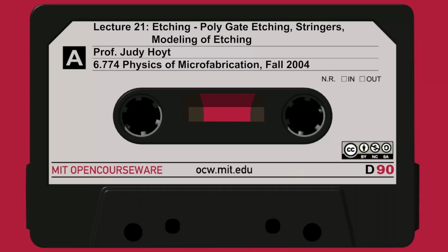So this is an example of how they got rid of the notch. This notch is not as bad or doesn't look as dramatic as the one I drew on the board. They got rid of it by just changing a few things. They changed the pressure and the flow rate, and they're able to get a more vertical type of sidewall. So if you have to do polysilicon gates, you'll find yourself twiddling a lot of the knobs, the pressures, the flow rates, and things like that, until you get a shape that you're happy with.